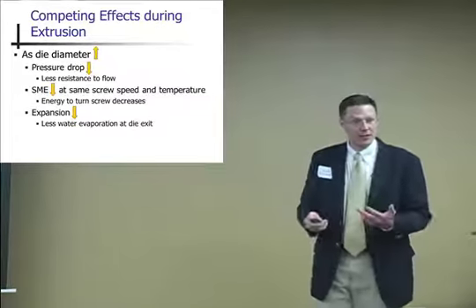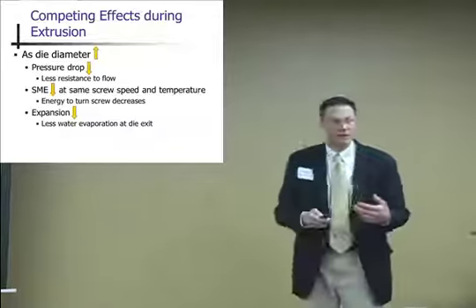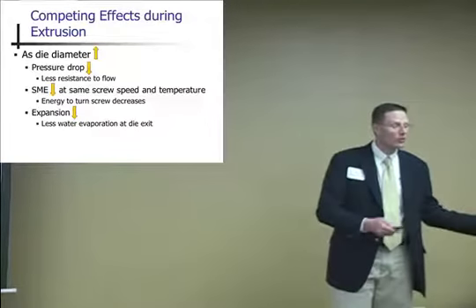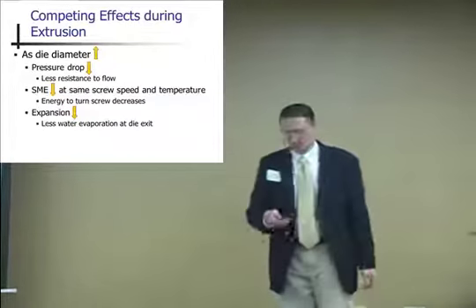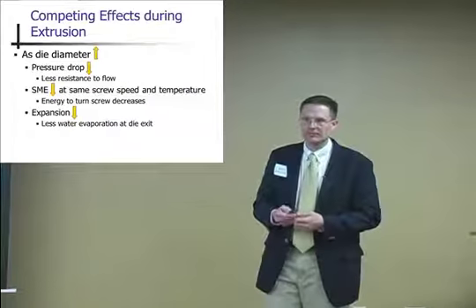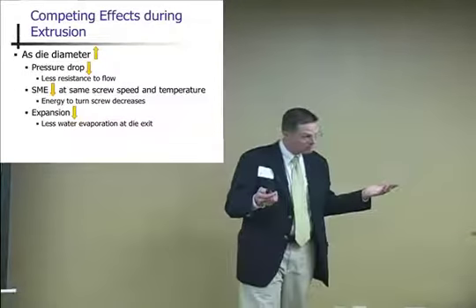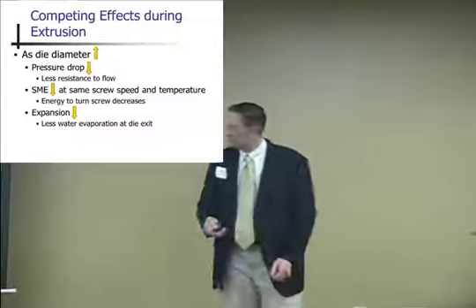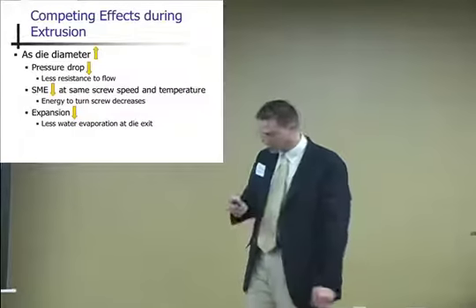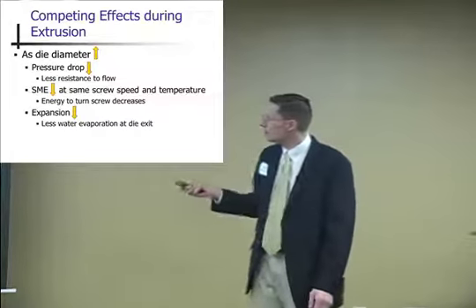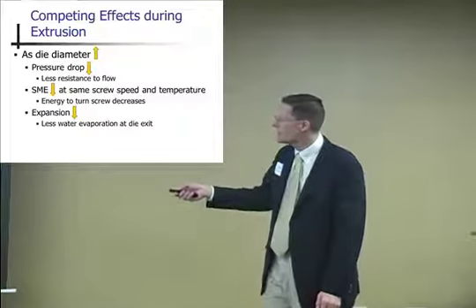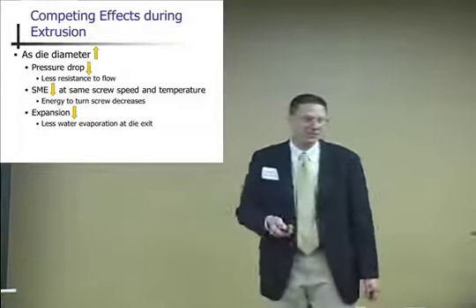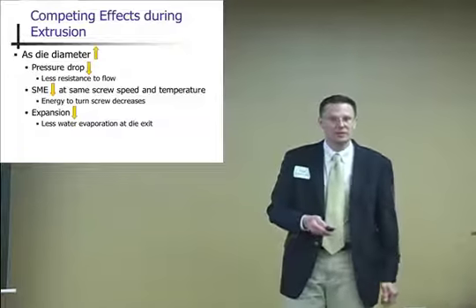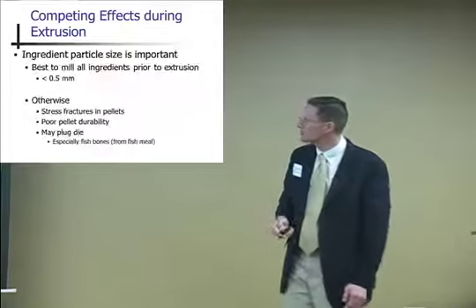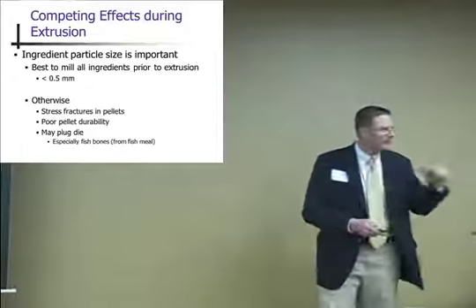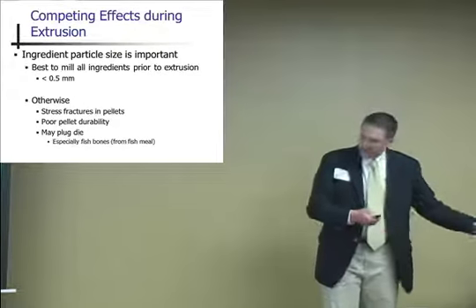As your die diameter goes up, if you use a 3 millimeter versus a 2 millimeter, or a 4 millimeter instead of a 2 millimeter, and why would you want to do that? Different size fish. Obviously your ingredients are going to change to some extent, but as your die size increases, your pressure drop is going to decrease, your SME is going to decrease, and your expansion is going to decrease. So you're going to have to change something else in the process. A lot of competing effects. Something to think about.